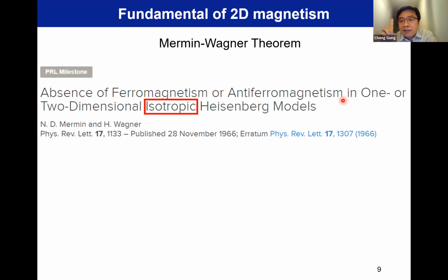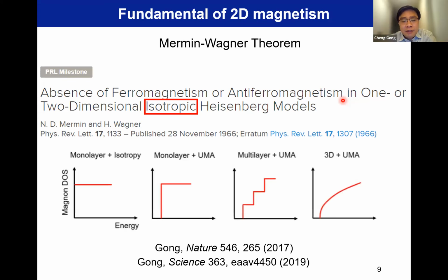Classically, you can imagine that if you have an easy axis anisotropy, in order to randomize the spin, you need to overcome the anisotropy, right? But you can also understand this from the spin wave excitation picture. This kind of analysis has been presented in these two papers in detail if you want to read more. If you have a 2D system, let's start from here, and you don't have any easy axis anisotropy, you don't have any spin wave gap opening. So at any finite temperature, you can easily excite a lot of density of states. Plus the divergent statistics here, you will totally destroy the magnetic order.